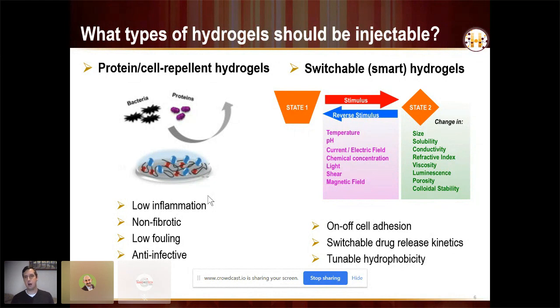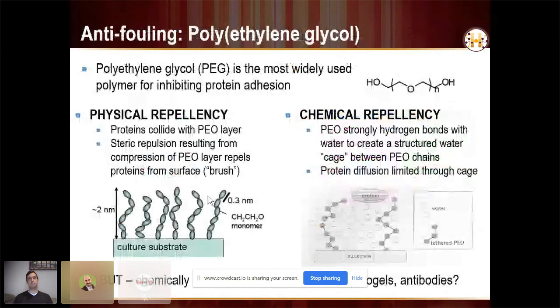This has attracted a lot of attention in biomedical applications for things like on-off cell adhesion. So we can tune the cells from sticking to releasing, switching drug release kinetics. So we can turn drug release on and off to make release vehicles last longer and reduce side effects when drug is being delivered when it's not really needed. Or tuning the hydrophobicity, so tuning the interface, so how the body will respond to a particular implant or material over time. So the typical materials that we use for these, for antifouling, by far the most common is polyethylene